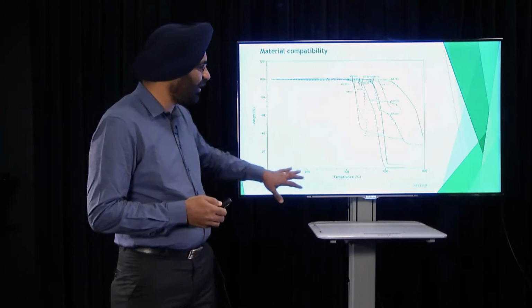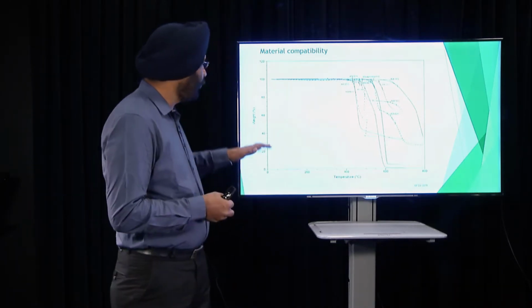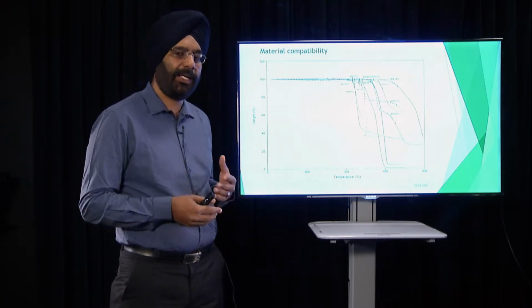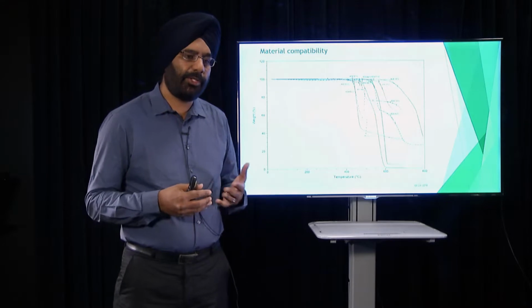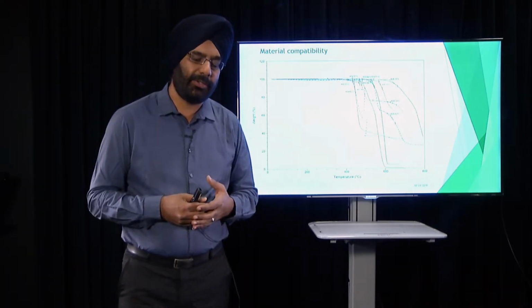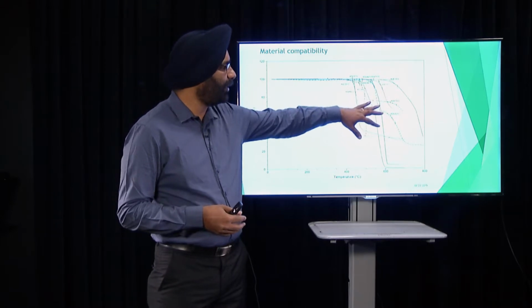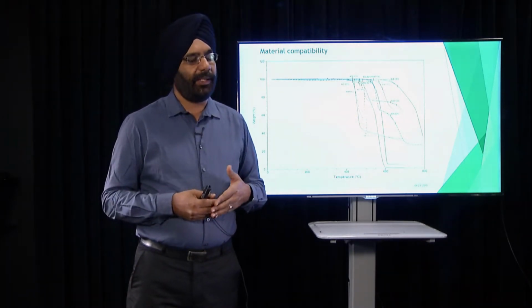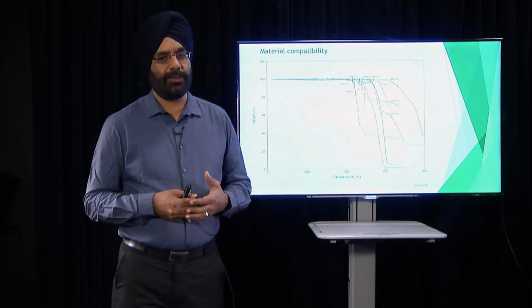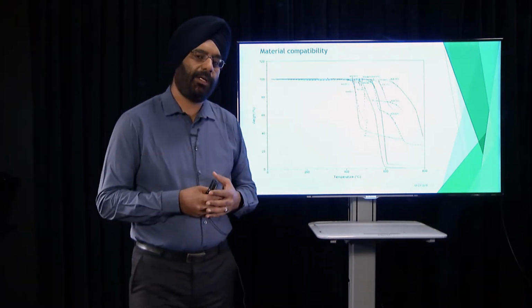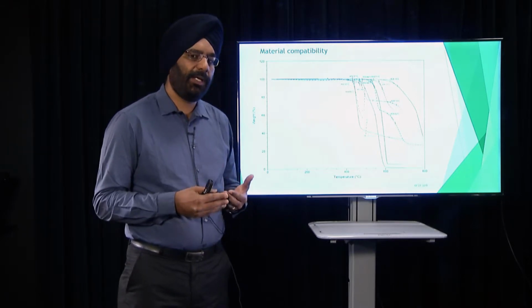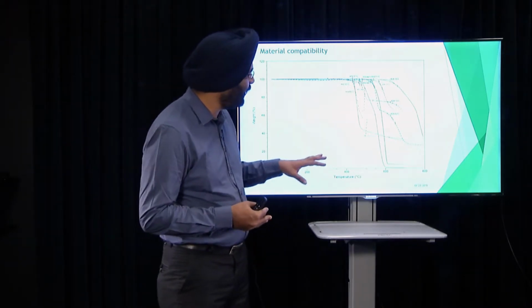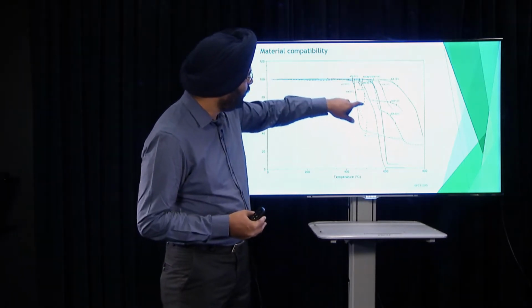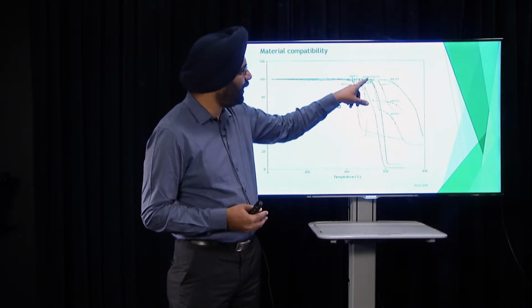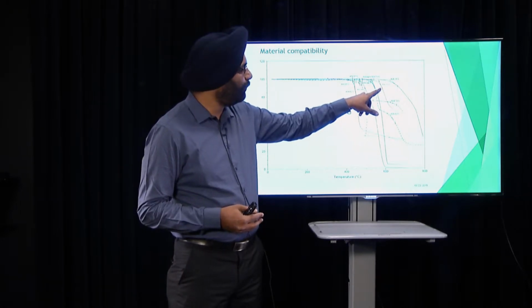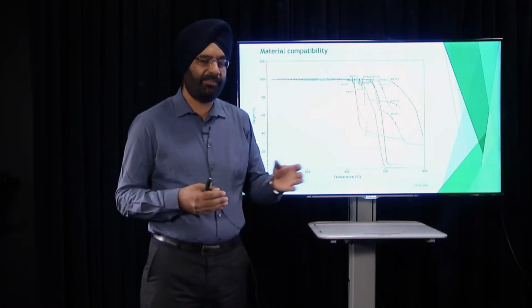Now this is a TGA graph, a thermogravimetric analysis graph. What we did is we took the polymer and mixed it in with the molten salts, and heated it to a certain temperature. We saw, in the absence of salt, the temperature where the polymer decomposed, and when the salt is present, what the decomposition temperature is. As you can see, I can give you an example here. If you see this purple line, in the absence of salt, the polymer decomposed at around 570 degrees C,